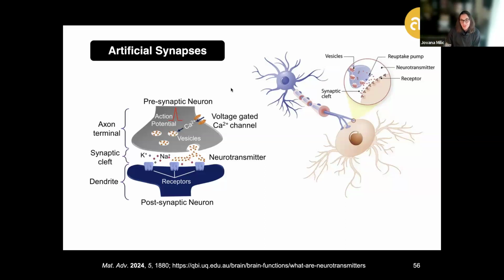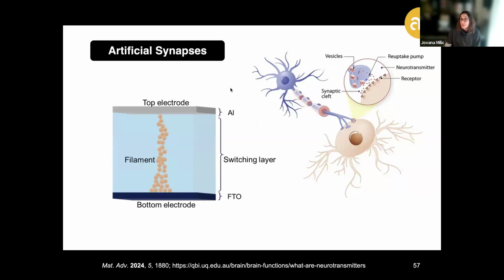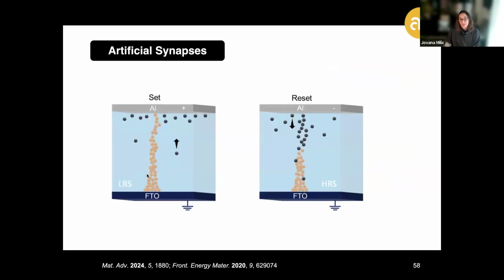Hybrid halide perovskites provide a unique opportunity to address this by relying on their mixed ionic and electronic conduction, which through certain voltage biasing in relatively simple device architectures can contribute to the formation of conductive filaments based on ions or vacancies, mimicking resistive switching systems. The conductive filament can be set at a certain voltage, forming a lower resistance state, or reset at another bias where rupture of the filament leads to a higher resistance state - forming a so-called resistive switch that can act as a memory element, providing different memory states tailored to mimic natural systems.